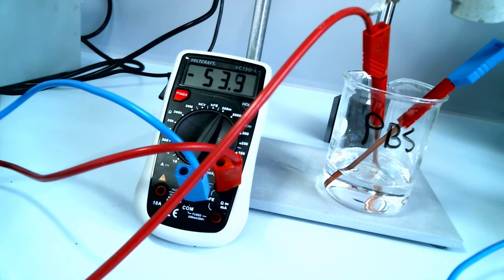Copper is very stable here. It is saline, but it's buffered, so we're not running away in pH. So we would expect this to eventually settle down. It'll take a long time, but it'll eventually settle down, and we would see a difference in voltage between the two. But it won't be very high because obviously even the shiny one has a little bit of oxide on the surface, so that they're not that different.